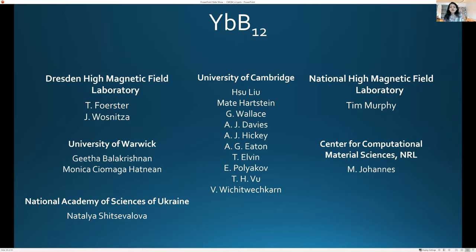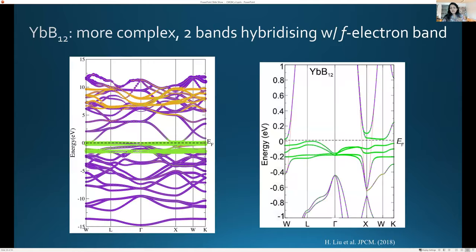Okay, so again, this is an example of a Kondo insulator. In this case, there are two conduction bands that cross the Fermi energy. So the one here around the X point and the one here around the W point. And so what this means is one has a more complex Fermi surface. There's still a gap at the Fermi energy, but if we were to think of what the conduction electron Fermi surface might be, it would be more complicated.